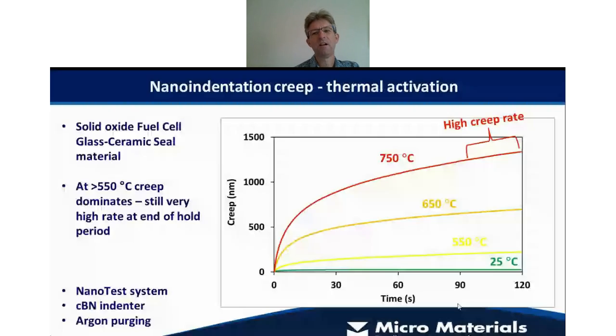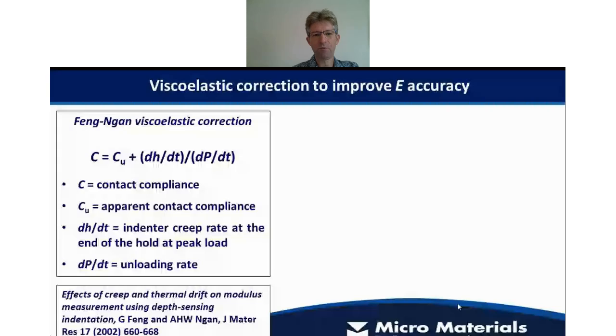So you can imagine that the creep rate is continuing as you unload, and therefore it's affecting the contact stiffness. This is a headache for nanoindentation data, and we need to handle this either analytically or essentially get around that if we want to get accurate elastic modulus measurements.